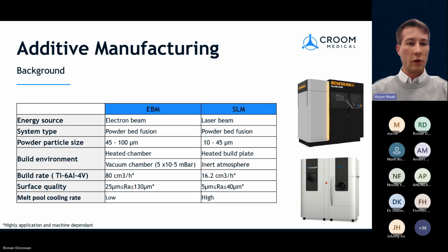In my talk, I'll focus primarily on two key technologies: electron beam melting and selective laser melting. There are some differences in those technologies. I'll just briefly mention that electron beam melting, of course, uses an electron beam as its energy source, while selective laser melting uses a laser. E-beam generally has a larger powder particle size, which results in a faster build rate, but can reduce the surface quality somewhat, although with the caveat that this is highly machine and application dependent.